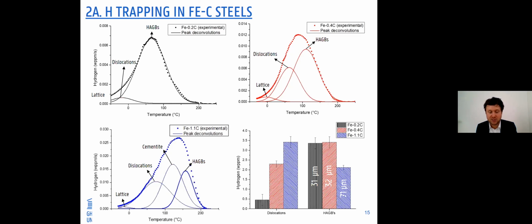When the prior austenitic grain size was the same, about these 30 microns for the 0.2 and 0.4 carbon steel, the content of hydrogen was similar. But when the high angle grain boundaries were lowered, because the prior austenitic grain size increased to 70 micrometers, this also comes with a lower hydrogen content. So this is a proof that the concentration of hydrogen is reduced because of the larger grain size.